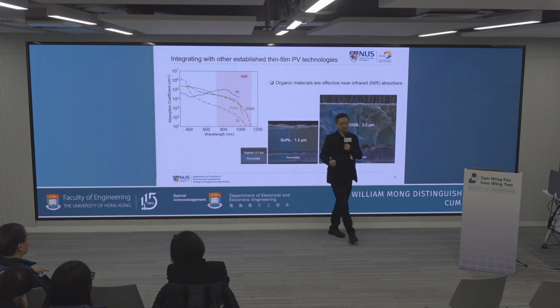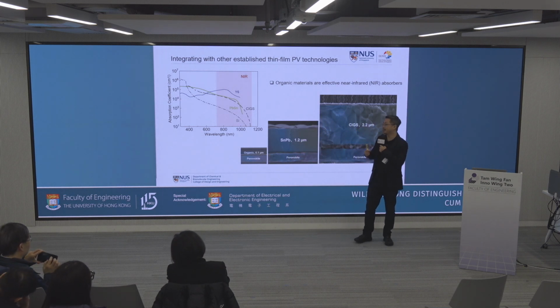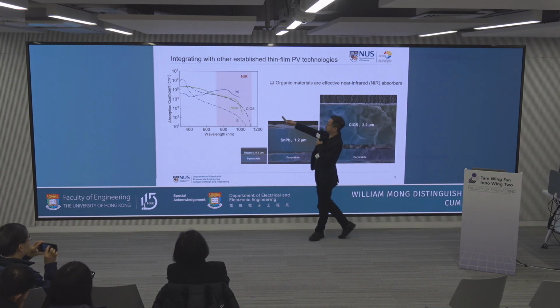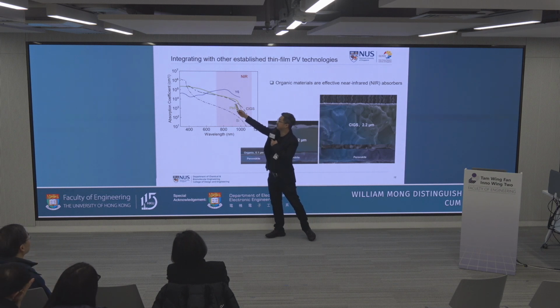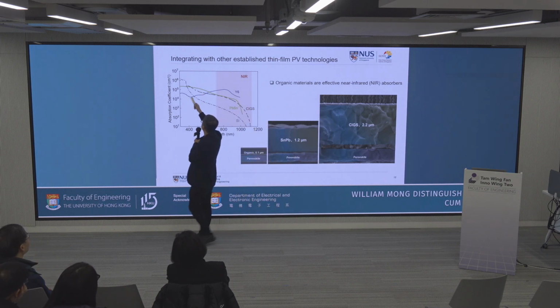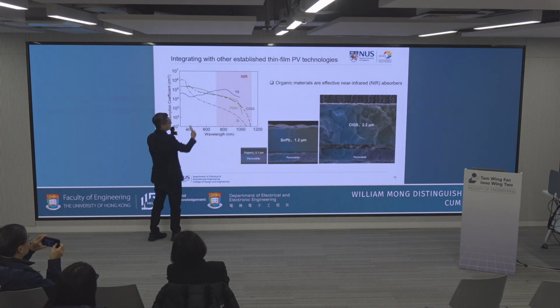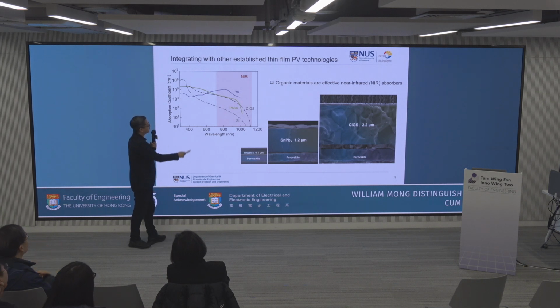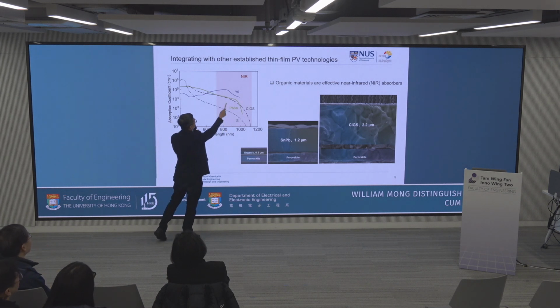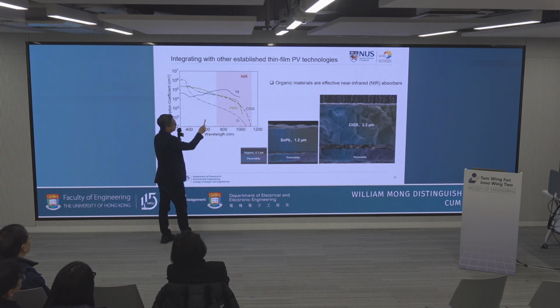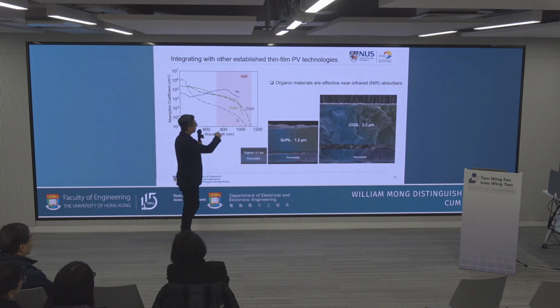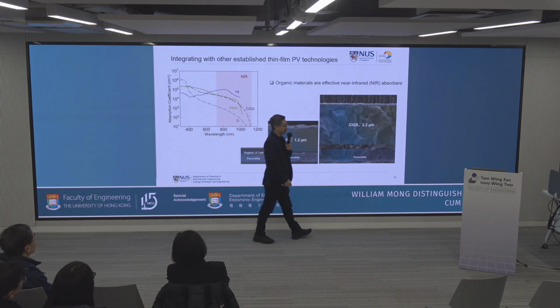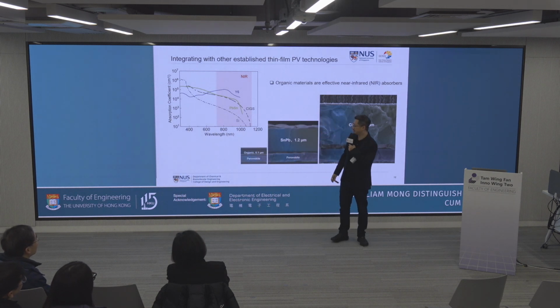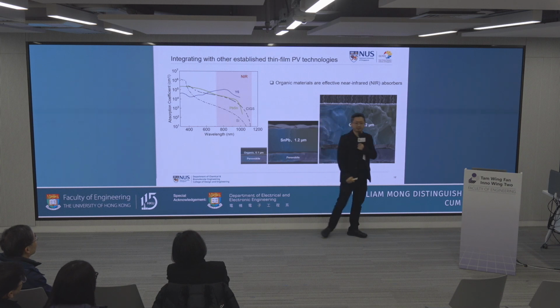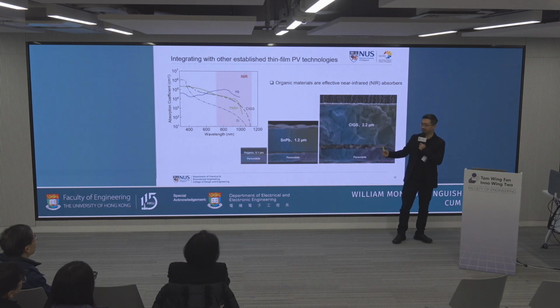So because organic has a very strong absorption coefficient in the near IR. If we take this Y6 as an example, it's not a good absorber in the visible. If you look at the absorption coefficient of this one, it's not very good. But if you look at the near IR absorption coefficient, the Y6, this organic material is much better than all the other components. So this gives us an opportunity to make this bottom cell very thin, about 100 nanometer. We can capture most of this